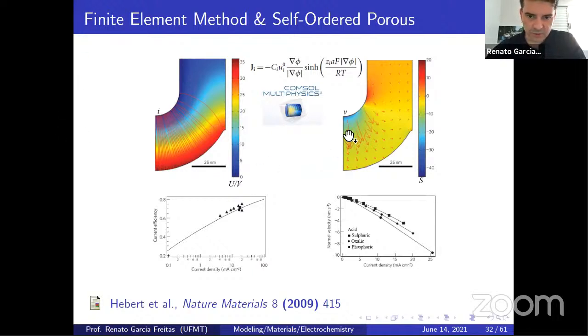So we observe that we have a stress down there. So we read this paper and we thought, oh, for sure, they observed the stress, and it induced the stress because you see here, the stress is quite higher here and not here. I must spotlight here that it's a dielectric oxide, isn't it? So the electric field is quite higher here than here. Aluminum is a conductor, but aluminum oxide is a dielectric, like titanium. Titanium is a conductor, but titanium oxide is a dielectric.